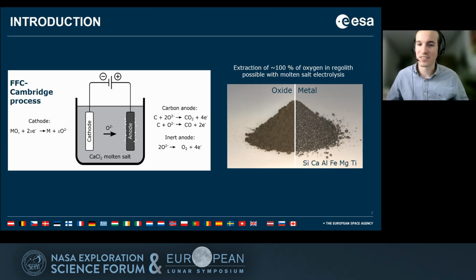I think this slide, this picture of the regolith before and after, has been shown by quite some people in our community before. But just to make things clear, this is really all the metals. It's not only titanium. So we are not relying on ilmenite or a specific mineral, but we are really able to extract the oxygen from every silicate and every mineral on the moon, to our knowledge. The mixture you get in the end is a mixture of silicon, calcium, aluminum, iron, magnesium, and titanium.